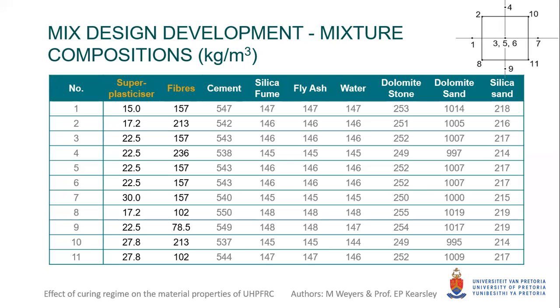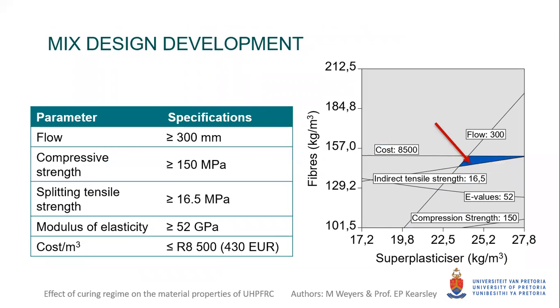Relatively low cement content is used compared to other ultra-high performance concrete mixtures, which can go up to about 1,000 kilograms per cubic meter. Coarse aggregate was also incorporated in the mixture design, which is not the norm for ultra-high performance concrete. The responses obtained from the central composite design were used to optimize the combination of fibers and superplasticizer to give the optimum performance in terms of acceptable mechanical properties.